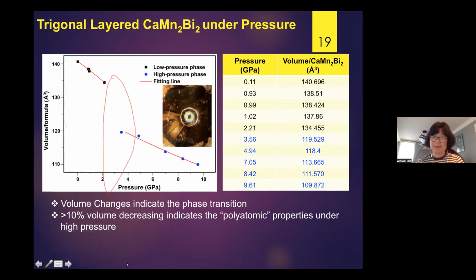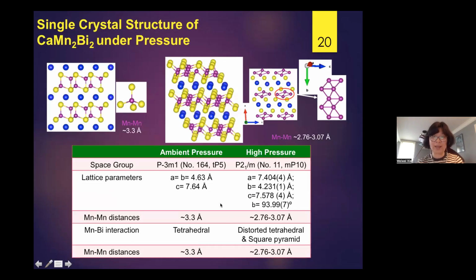Because we did single-crystal X-ray diffraction under high pressure, we can solve the crystal structure. Different from the high-pressure, high-temperature treatment, if we just use high pressure at room temperature, we do not get the trigonal phase; we get a monoclinic phase. This is the ambient-pressure phase, with a calcium layer and a manganese bismuth layer. Here is the high-pressure phase. It is still a calcium layer, but manganese and bismuth get much closer to each other, so they make a zigzag chain, a polyatomic system.